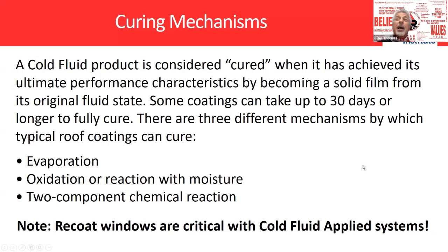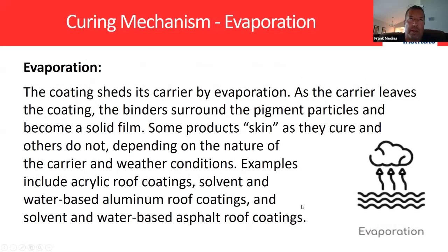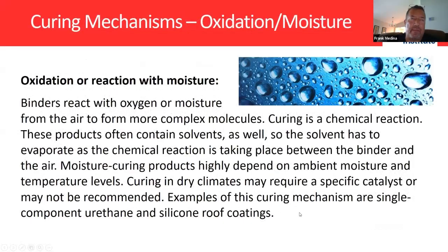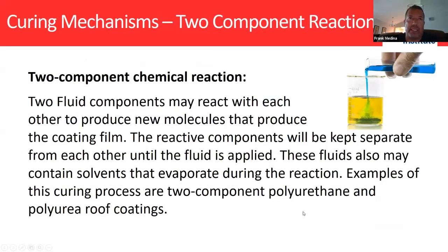Frank, on that project you're on, recoat windows, what do you look at between the time you put the first coat down and the time that you put down the successive coat? And if you don't hit that window for any reason, what do you got to do? Well, what we're doing on this building, we're doing on a Fort Myers, is that we're doing a 2-part epoxy primer. Once we put the primer down, the dry time is 3 to 4 hours. And then after that, we put down the first base coat, and then we immediately press in the fleece polyester, and then we follow that immediately with the second base coat. And then we wait, and we'll come back the following day. We have 3 days to come back to do the top coat. And that's for the Tremco products.